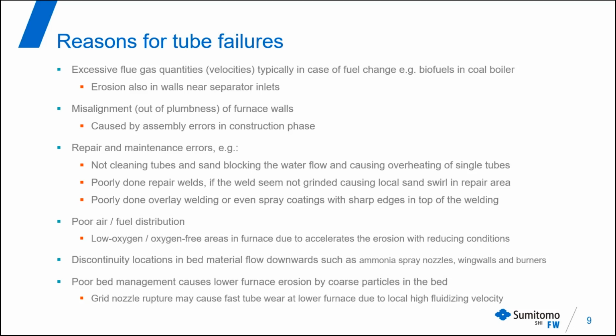From a corrosion point of view, the most common issue is the reducing conditions in the boiler, that is due to poor air and fuel distribution and mixing in the furnace, so that it will cause the atmosphere to be more aggressive towards the steel and cause local wastage of the tube material. Also, ruptures of grid nozzles might cause local issues with the circulation and high velocities in the lower parts of the furnace, resulting in high erosion wastage in the tube.